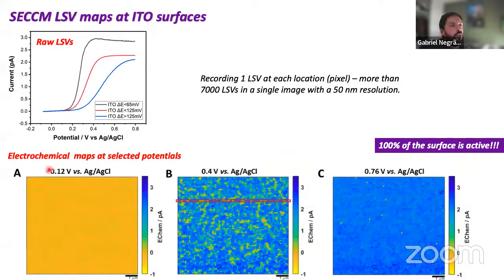If I'm at a negative potential, where I should not see any oxidation of the species I have in solution, roughly here, I can see that everyone has zero current. So the entire surface has no current, as expected. As soon as I start increasing the potential, and it's quite nice to see here around 0.4, I have a massive contrast. I have areas that have a large current, so 3 picoamps or more, and I have regions that still have 0. This is alluding to the fact that I have regions that are quite fast and regions that are quite slow. So at a given 0.4 volts, if I put a line here, I have regions that are already in steady state and regions that are just getting there. But again, none of the surface is inactive. And of course, if I go very positive, I'm getting to limiting steady state for everyone. There's a different current here between 2 and 3, but everyone is active.